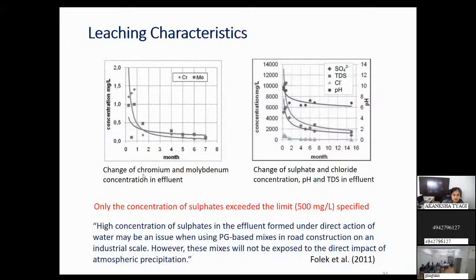And they found that the concentration of chromium, molybdenum, and in fact TDS, chlorides, and pH reduced with the months, with time. So with time, the reaction is taking place, and all these leachate concentrations came down, and they found only the concentration of sulfates exceeded the limit. But you know, this was the paper by the Transportation Research Board.